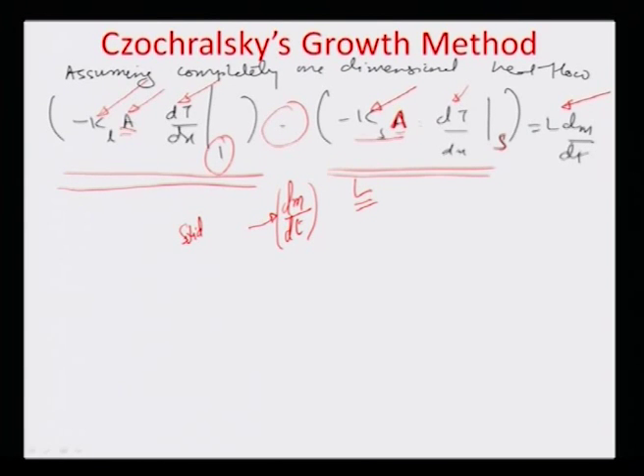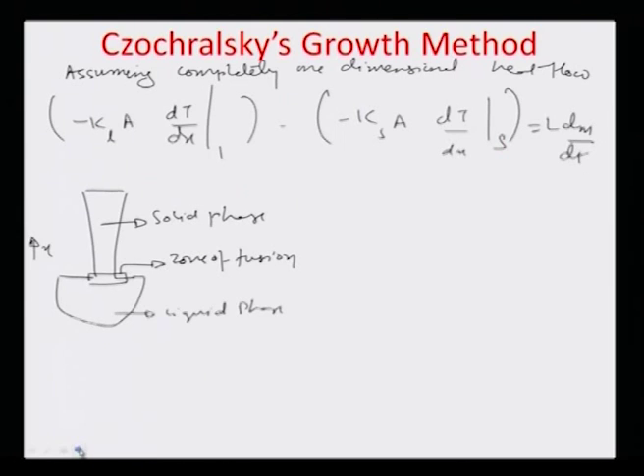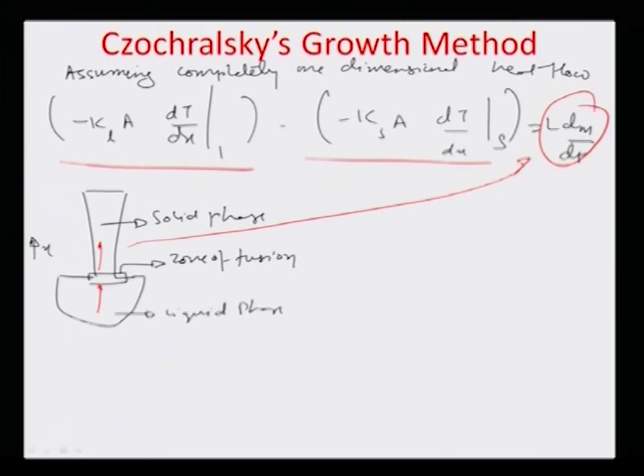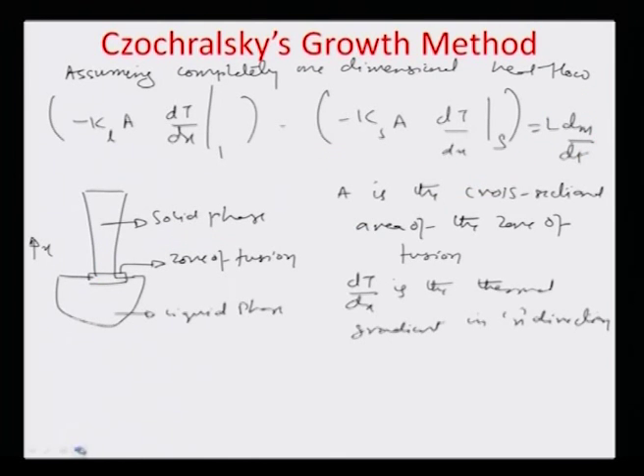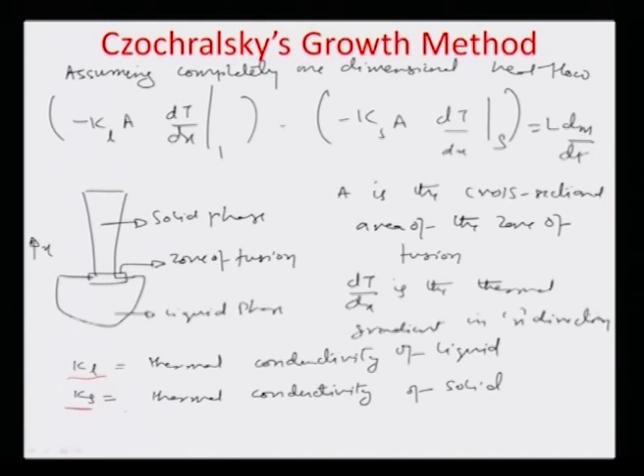So, you can really equate both these equations, and that forms the basis of the Czochralski growth process, because, you know, heat flowing in here is represented by the first term, heat flowing out here is represented by the second term, and in between whatever is happening results in this formation of the solid phase, the dm by dt. So, that is really what this Czochralski process is about. dT by dx of course is the thermal gradient in the x direction, either from the liquid to the zone of fusion, or from the zone of fusion to the solid, and KL and KS are respectively the thermal conductivities of the liquid state and the solid state of the silicon.